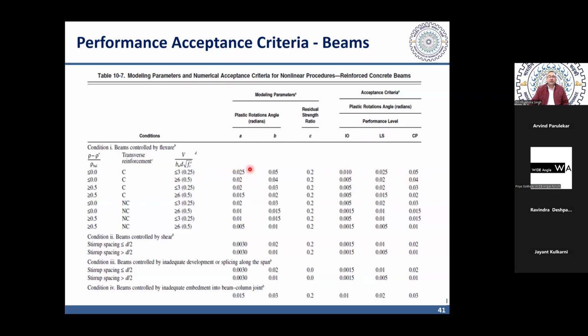You see the value of a, till there is drastic reduction in the strength of beam, this value is 0.025 radian. And b, where the collapse occurs, it is 0.05. And you can see that the value of CP is same as the value of 0.05. So if the plastic rotation exceeds 0.05 radians, the collapse of that member, that beam, will take place.